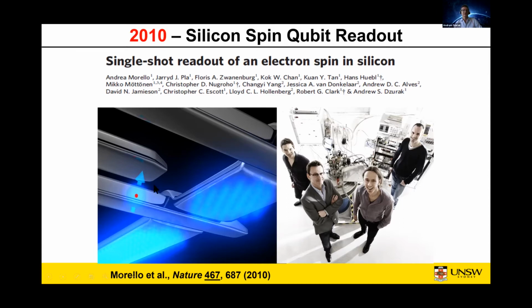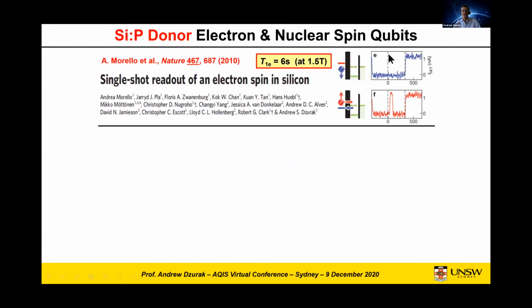And the measurement of the spin on this single atom is done by monitoring the current through this single electron transistor. So if we go now back to the next slide, this data here, taken from this paper in 2010, is showing the current measured between 0 and 1 nanoamp through that transistor device on the chip as a function of time. So sorry, this time's been cut off. This is up to 500 milliseconds here on this time scale.